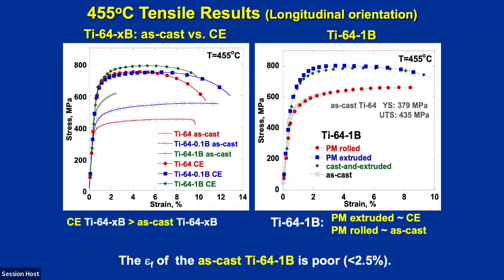And if we look at just the as cast, again, that was the one with the least amount of elongation with the 1 boron. And then the powder metallurgy rolled doesn't quite reach the same strengths as the powder metallurgy extruded. Again, probably because of the texturing effect.